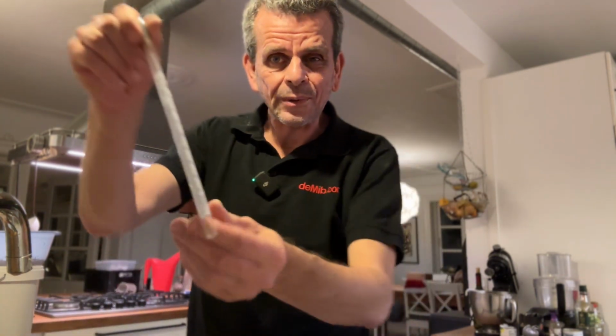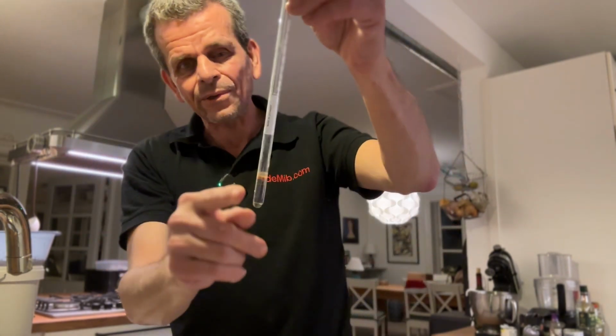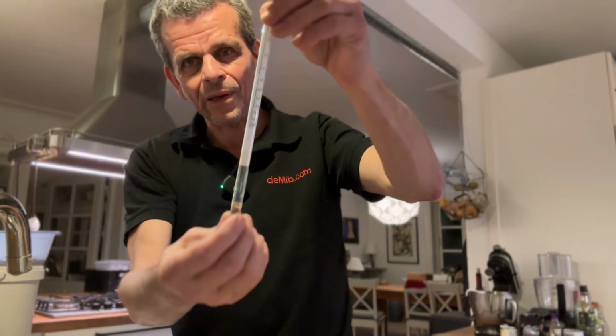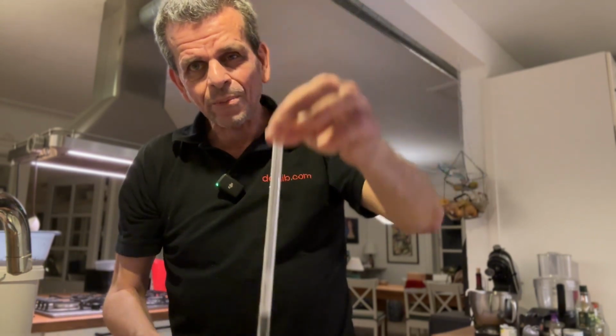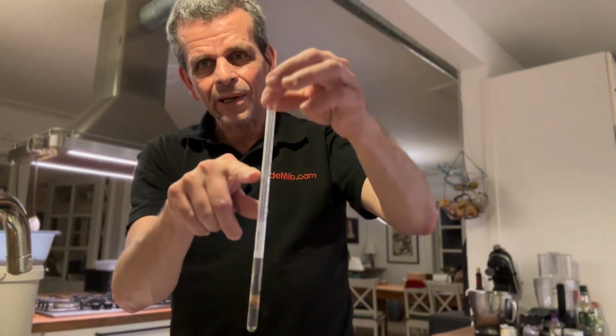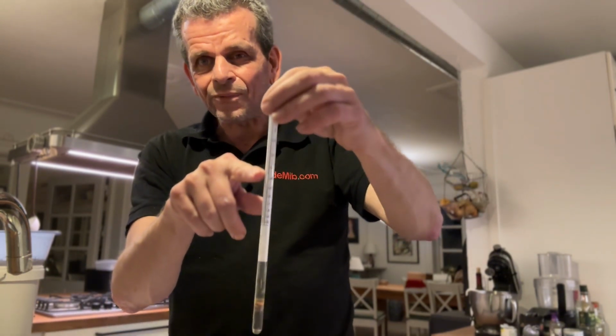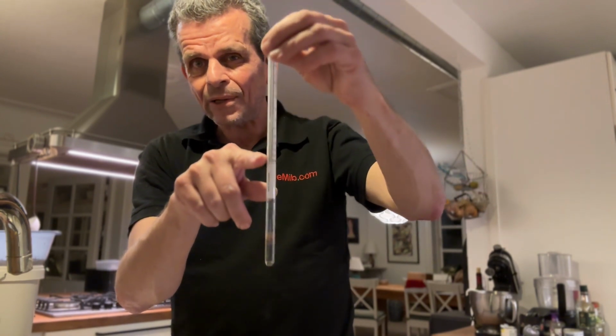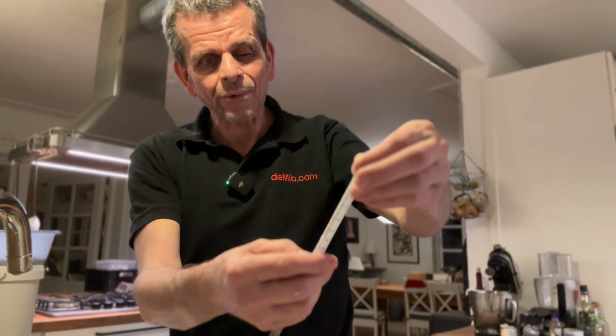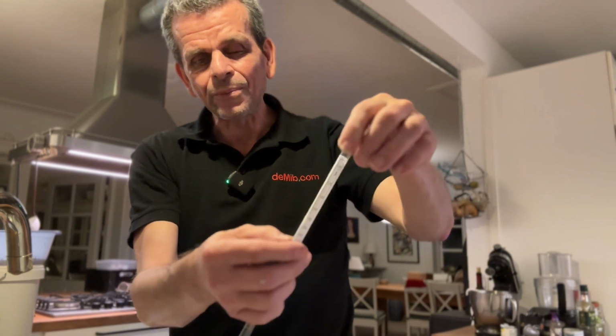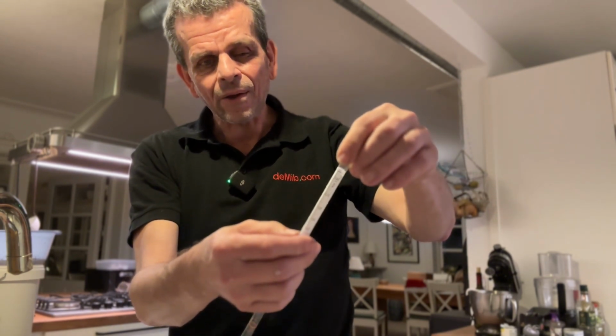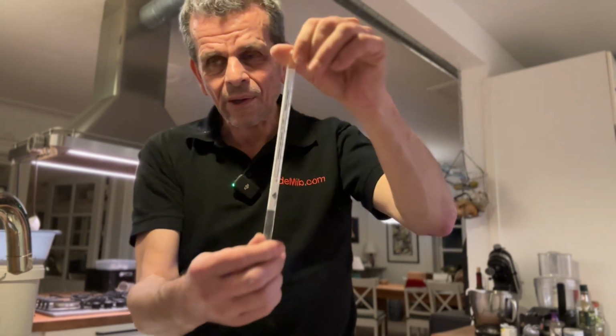I think one of the most common methods is with a hydrometer. This is this glass thingy that has some lead in there or something heavy in the bottom, and you put it into a bucket, and it will sink deeper if there's more water, and it will stay higher if there's less water, and then you can read out the measurement. And typically a glaze would be somewhere between 30, 40, 50 or something.